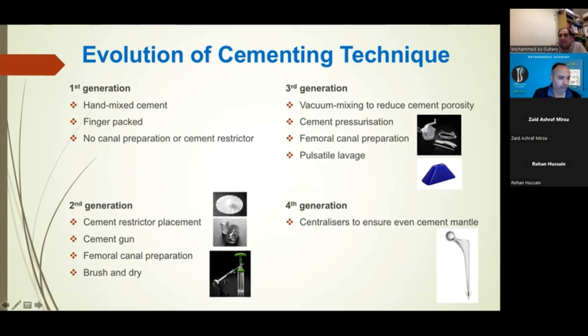Third generation introduced vacuum mixing to reduce air bubbles in the cement so you don't get problems with crack propagation. Cement pressurization I spoke about, using these triangular blocks in the proximal part. You may have seen people use that. And the introduction of pulse lavage, cleaning and washing out the canal really well. The fourth generation introduced these centralizers distally to make sure the stem is as central as possible in the canal.